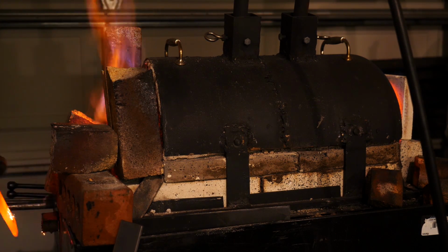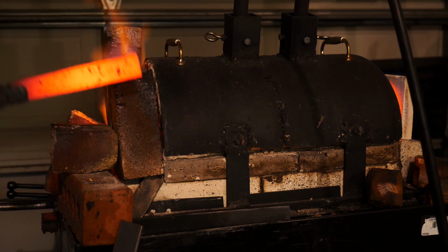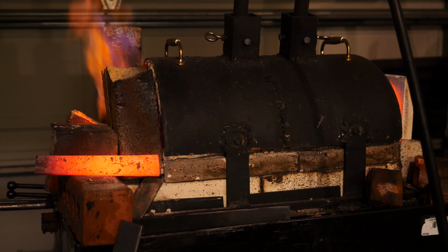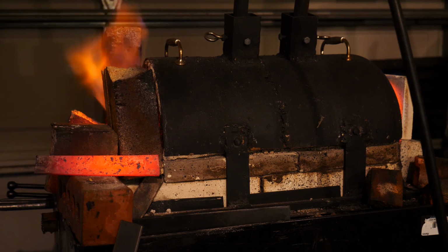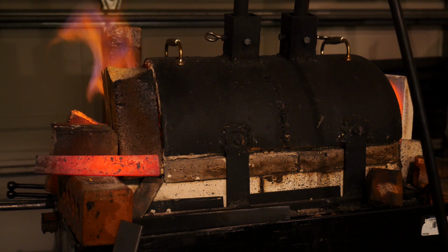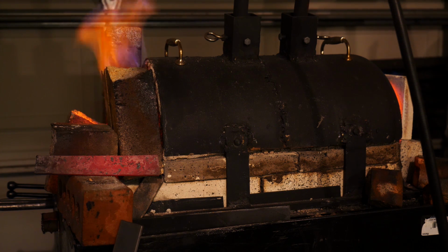So a lot of you are probably asking, why didn't you anneal anything? Well, 5160 is a hypoeutectoid steel. A lot of people don't anneal it to make knives with. It's really hard to anneal. You really need a heat treat oven, and even then it's very difficult. You have to drop the temperature at a certain rate, then hold it, then drop it again, etc.